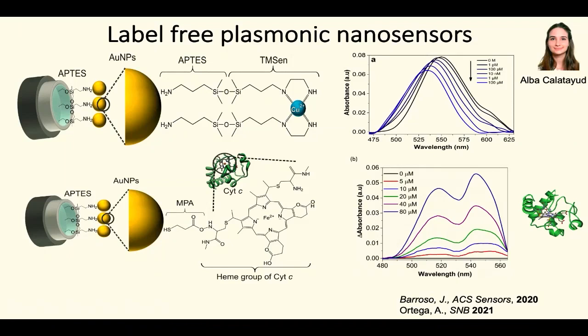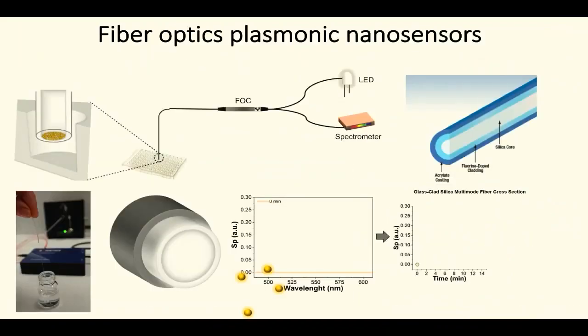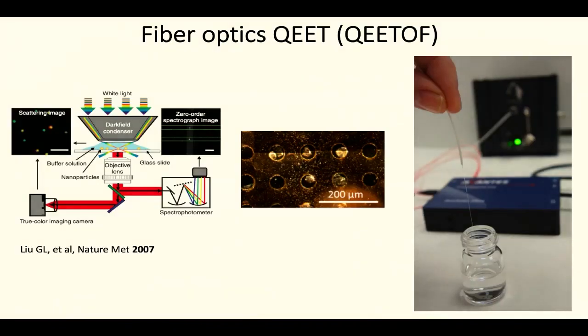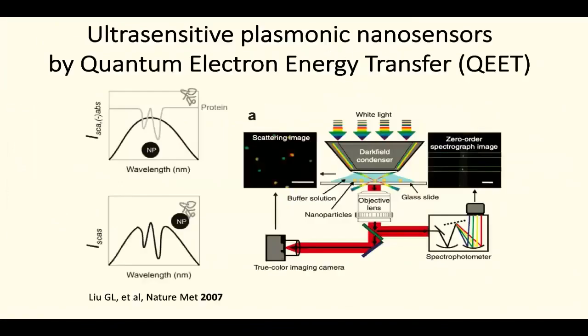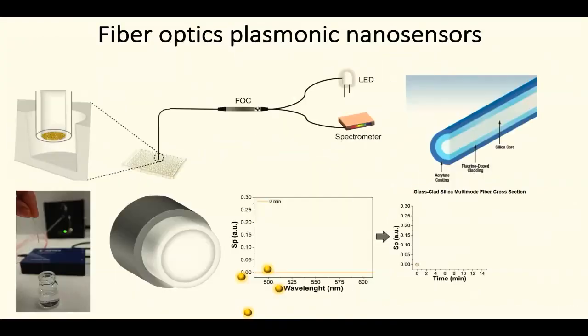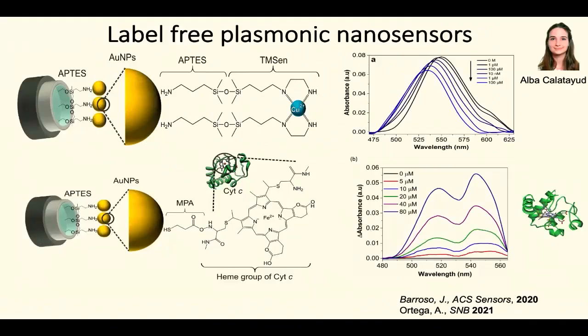The very interesting thing about this is that our sensitivity was 3 orders of magnitude higher than the sensitivity obtained with the dark field microscope. And to me, this makes sense because when you have the microscope, the light has to go through the slide, the objective, and all the optical path. So you lose efficiency. Instead, when you have the optical fiber, the light goes directly from the source to the tip and goes back to the spectrophotometer. So you don't have so many losses. And that's why we think we could increase the sensitivity of the system.